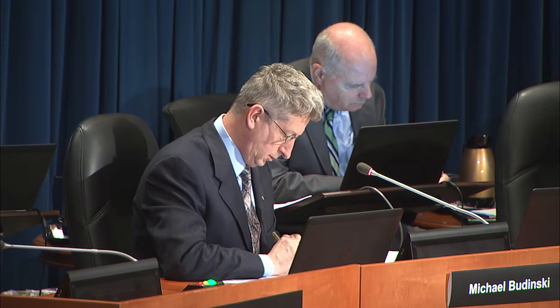Yes. The presence of the coating or not, from a material perspective, is irrelevant, but the loss of coating, as I described earlier, can lead to higher friction levels, which can raise the peak stress in the area of interest that we're discussing. So we have not confirmed one way or another, but as you said, we have seen blades that have a loss in residual stress.